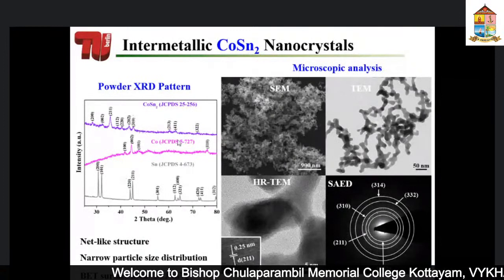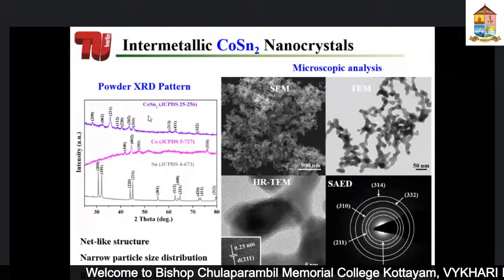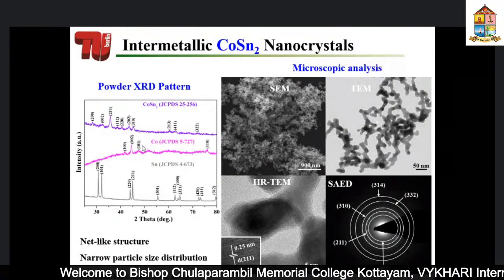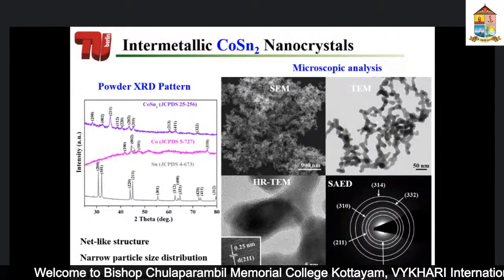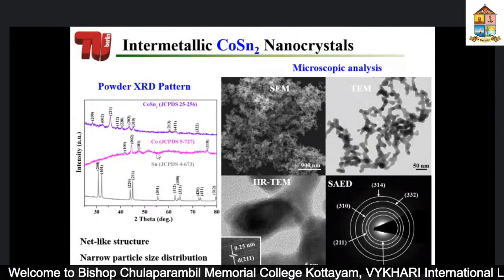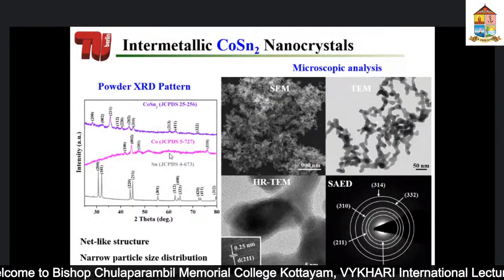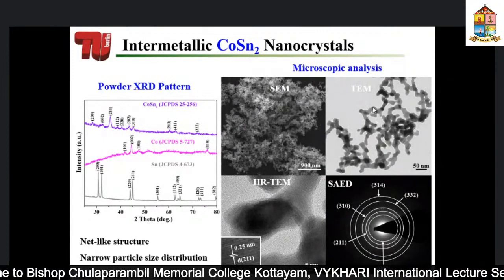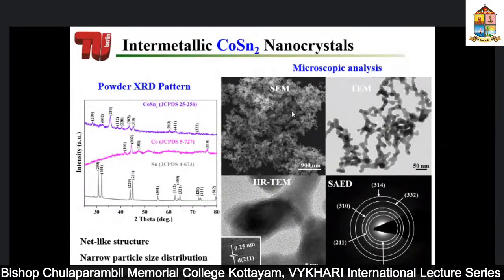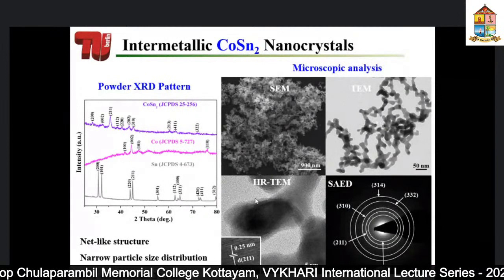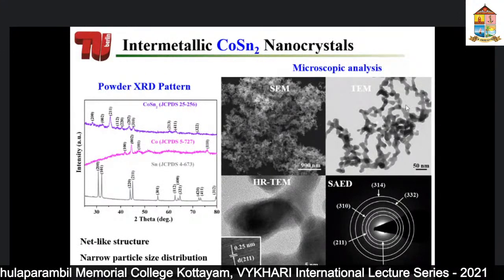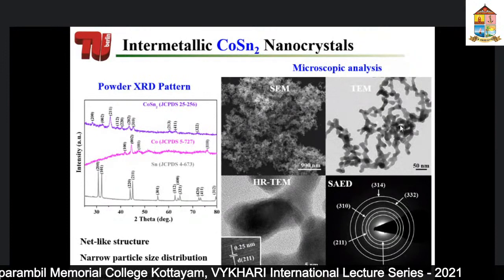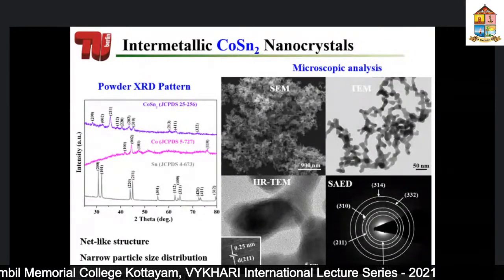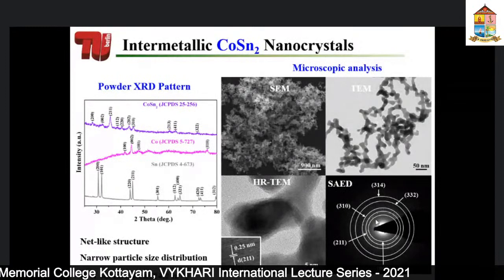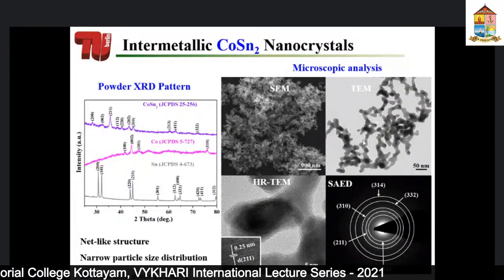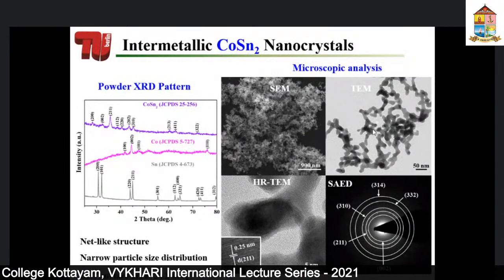This is again the X-ray diffraction pattern, which is very important to see whether we have made a pure phase. And what we see is that we have made a pure phase, and you see that it's a very weak diffraction pattern. That means you have a nanocrystalline material. So these materials, we looked into with transmission electron microscopy, and we also saw from scanning electron microscopy that they're very small nanoparticles and have made something like a net structure. And we get some rings in the selected area electron diffraction pattern. This ring is nothing but an indication that we have formed nanoparticles of very small size.